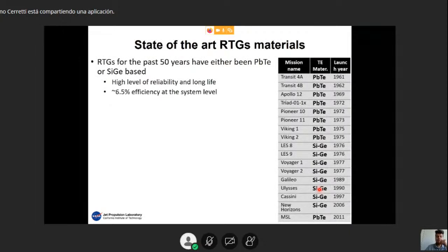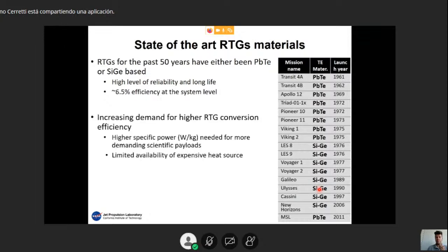So the state-of-the-art materials for the past 50 years, as I said, have been mainly lead telluride or silicon germanium-based materials. They had an extremely high level of reliability and long life, but the efficiencies were pretty low because we're talking about a top of 6.5% efficiency at the system level. We have increasing demand of power, so we need higher conversion efficiencies for the RTG. That means higher specific power is needed for more demanding space scientific payloads, and there's also the limitation of the production of the heat source, plutonium dioxide, because the process is really expensive and requires a really long time to produce the necessary amount for an RTG.